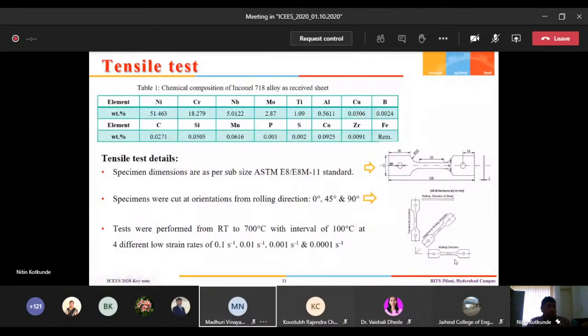Usually if you see our traditional tensile test machine, we conduct tests at constant speed, but for sheet metal applications we usually prefer constant strain rate. Constant strain rate is a different phenomenon. The increment of strain with respect to time is constant, meaning the increment of the strain value should be constant, not the speed. So usually the speed varies exponentially.